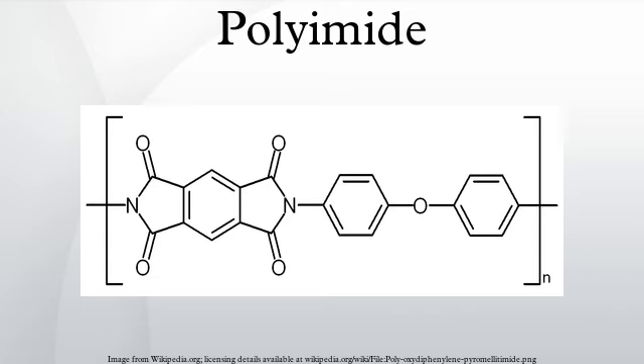An additional use of polyimide resin is as an insulating and passivation layer in the manufacture of digital semiconductor and MEMS chips. The polyimide layers have good mechanical elongation and tensile strength, which also helps the adhesion between the polyimide layers or between polyimide layer and deposited metal layer. The minimum interaction between the gold film and the polyimide film, coupled with high temperature stability of the polyimide film, results in a system that provides reliable insulation when subjected to various types of environmental stresses.